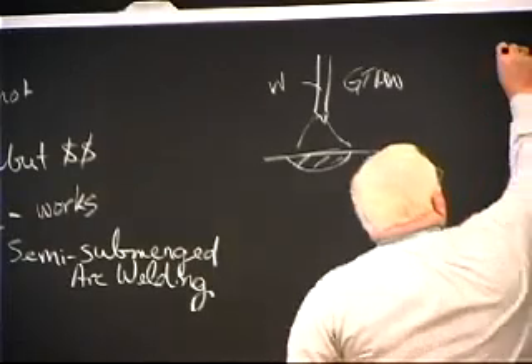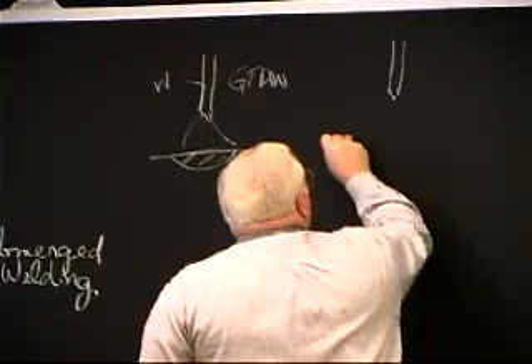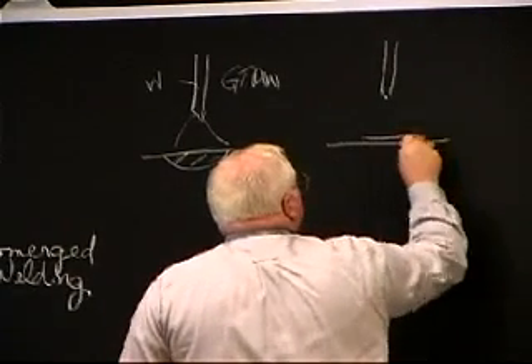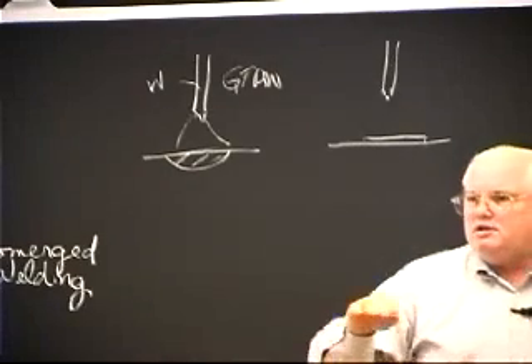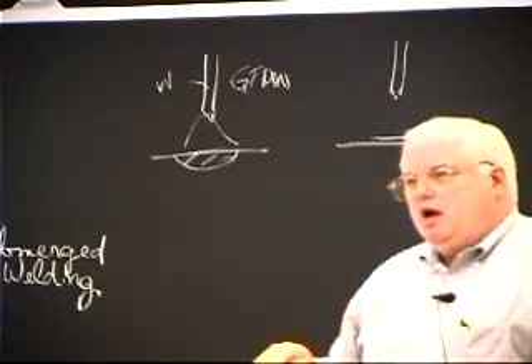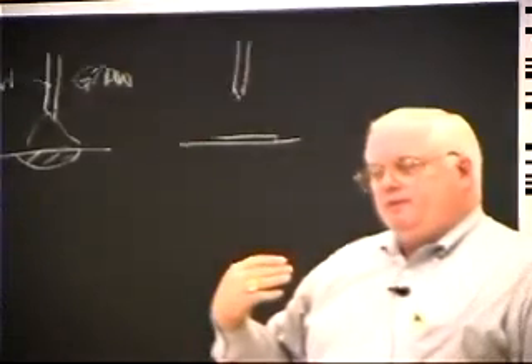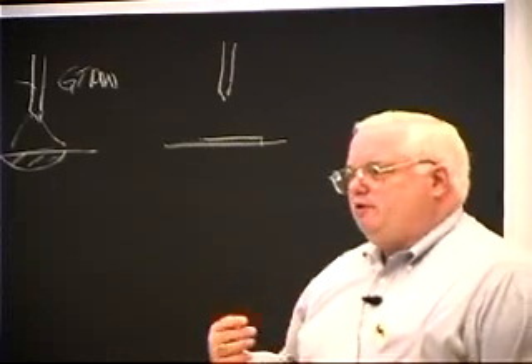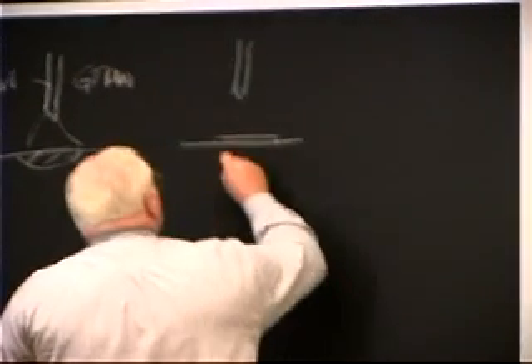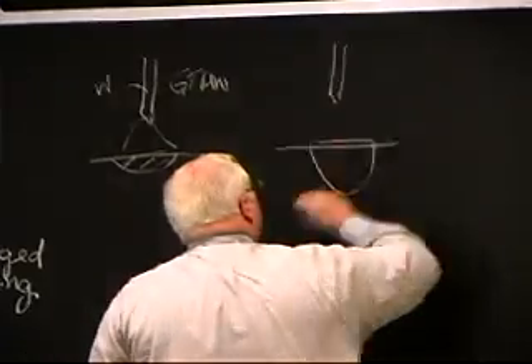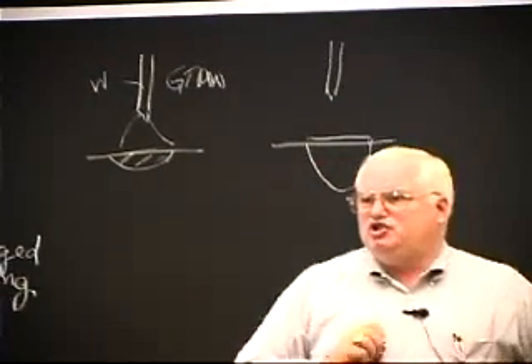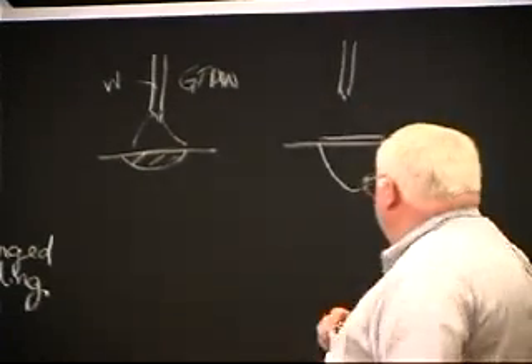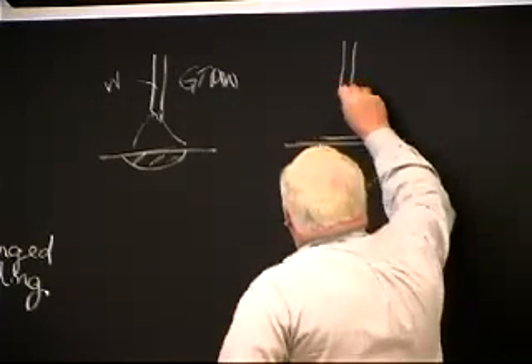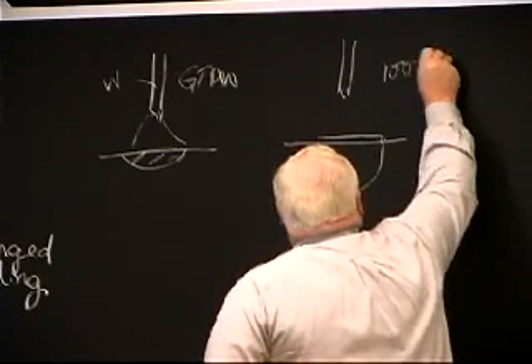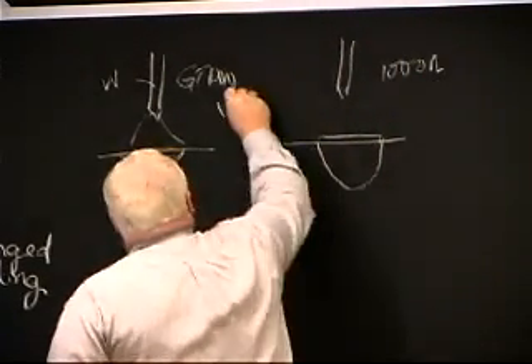It turns out the Soviets learned that if I put a little layer, just paint on a layer about a 1/4 millimeter thick of certain types of fluxes like strontium fluoride. They tend to be halides, fluorides and some chlorides. I could get maybe a 1/2 inch deep penetration, and I could run this arc up to 1,000 amps, whereas this one might be limited to 150 amps.